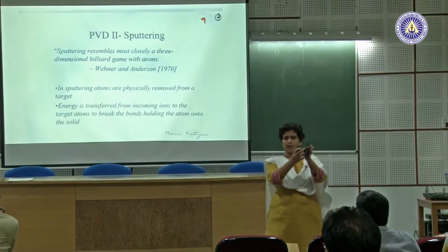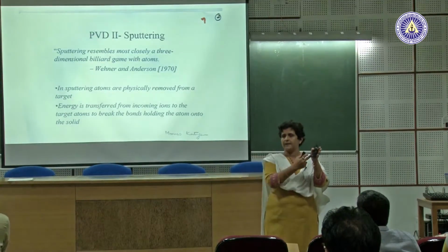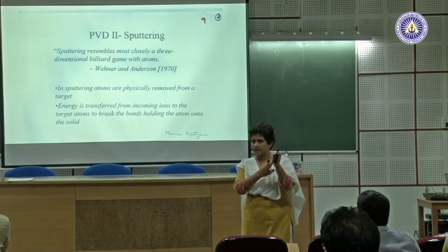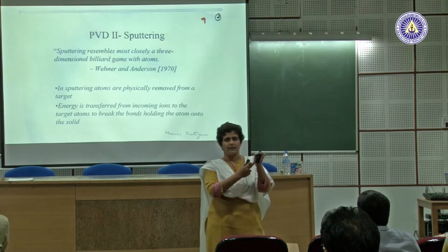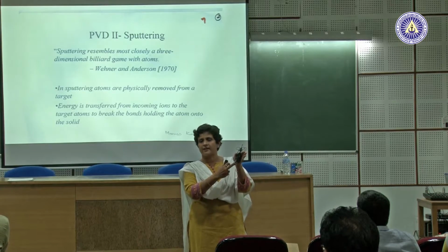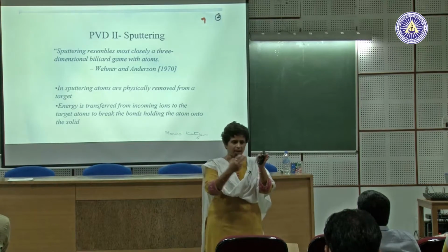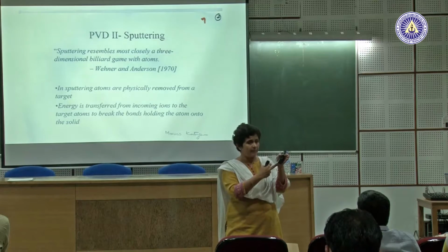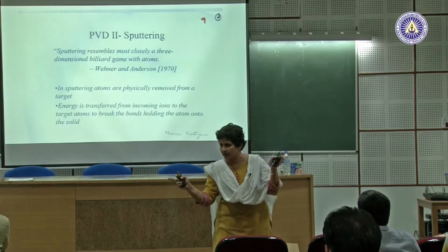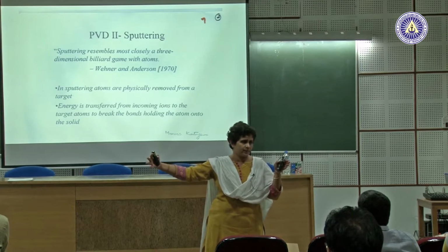Anyway, so what it does is, in sputtering, atoms are physically removed from a target. So basically, I take a target. Let's say I want to deposit aluminum film. I take an aluminum target, and I'm going to bombard that target with energetic ions, which are not going to react, like argon, right? This argon atom is going to hit an aluminum atom and is going to sputter that aluminum atom, which will be deposited on a substrate.